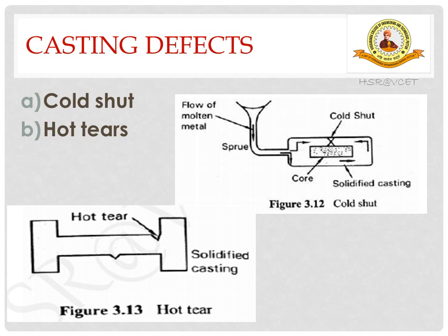In order to avoid these hot tears, we should provide adequate fillets at sharp corners while designing the components. Proper metallurgical and pouring temperature has to be maintained, and placing of gates and risers at suitable locations is very important.